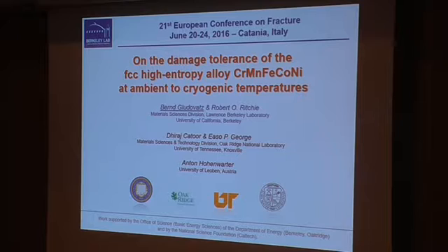In order to get now to the mechanisms that lead to such high fracture toughnesses, we have taken two samples from the two extreme temperatures, one at room temperature and one at liquid nitrogen temperature, and sliced them along the half, basically in the middle of the sample, embedded them both in conductive and non-conductive resin, and have done then a lot of microscopy in the vicinity of the propagated crack in the center of the sample, where we have full plane strain conditions.